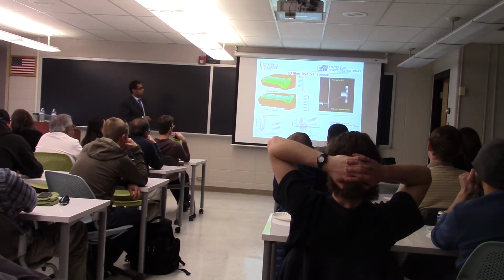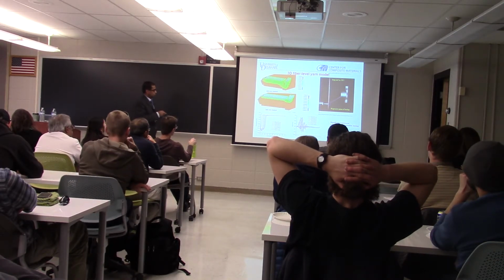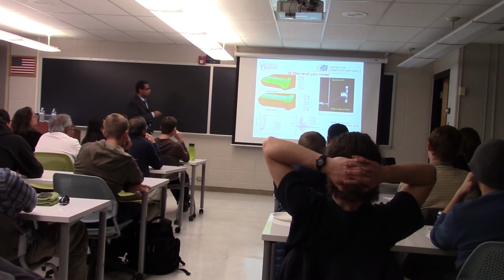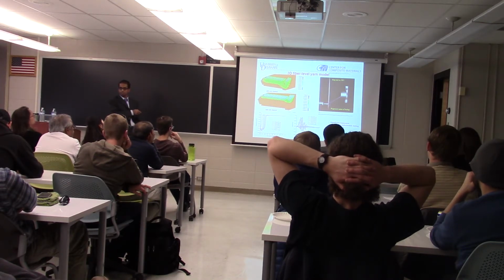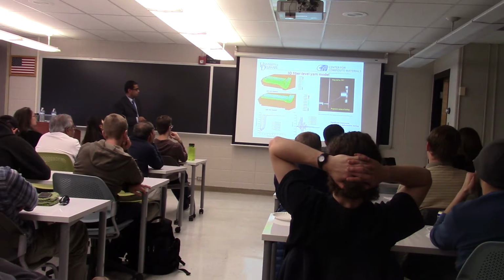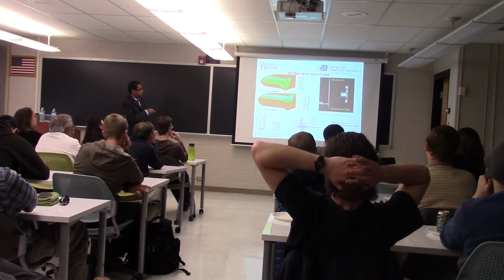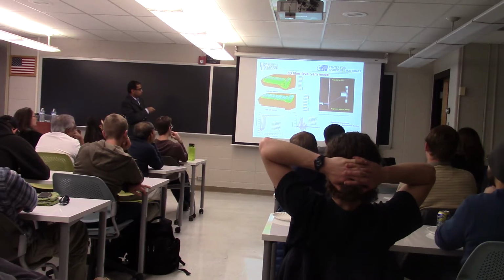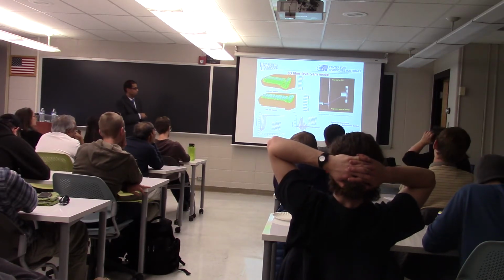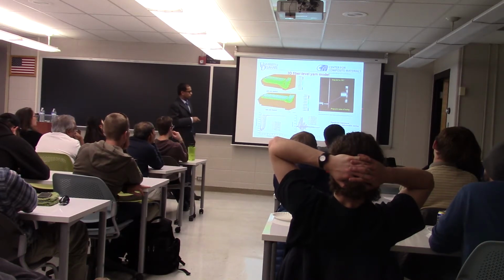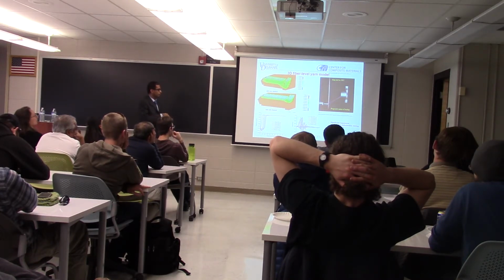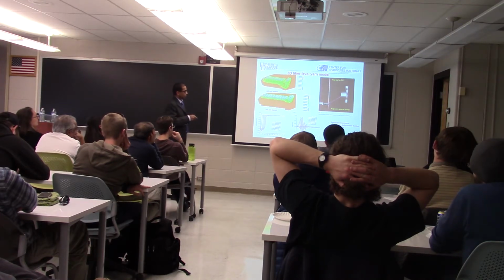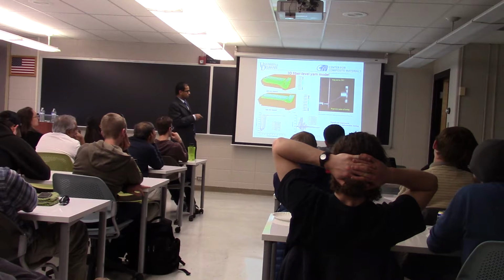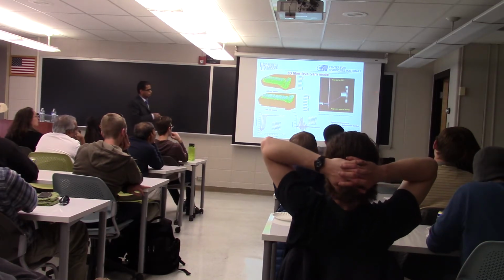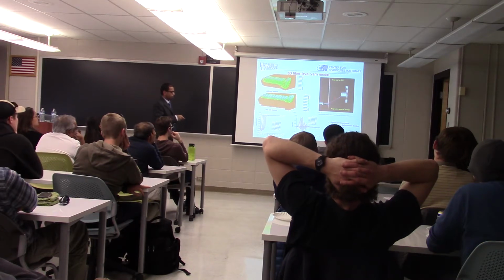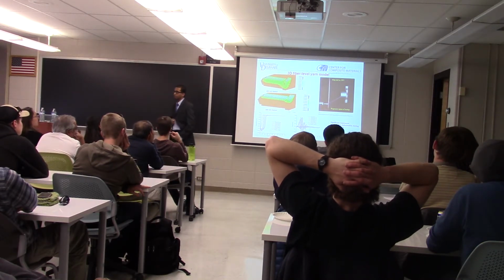Now, similar to the single fiber impact model, in this yarn model the fibers in the yarn also experience significant transverse compressive stresses and strains during impact. The fibers at the top row undergo initial deformation and then transfer load along the width and towards the bottom of the yarn through fiber-fiber contact. This is all consistent with the most recent experimental observations from Song and Lu from Sandia, where they showed that the fibers are impacted progressively along the thickness direction based on their high-speed camera images. They also note that the yarn behaves as a group of fibers rather than as a homogeneous medium.